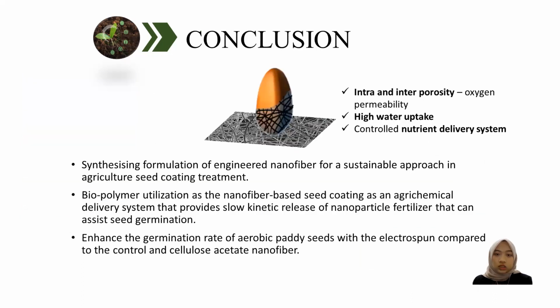As for the conclusion, this seed coating material from nanofiber has intra and inter porosity that can enhance the permeability and also has high water uptake, which are both important elements for seed germination to increase crop development and to enhance the germination rate of these aerobic paddy seeds. And with the morphology, structure and properties of the nanofiber, we are able to have a controlled nutrient delivery system. Thus, the conclusion of this study is that we are able to enhance the germination rate of aerobic paddy seeds through the application of cellulose acetate, zinc oxide nanoparticles, and electrospun nanofiber.